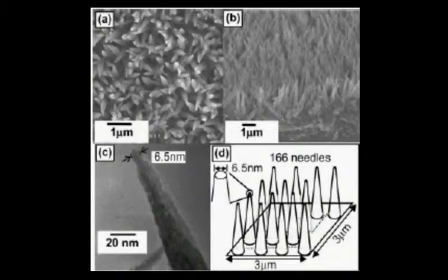Good results have also been achieved by using the bottom-up approach. In this picture, a nanoneedle structure was grown using chemical-based deposition. This nanoneedle structure gives a contact angle of about 178 degrees, which is the highest in the world.